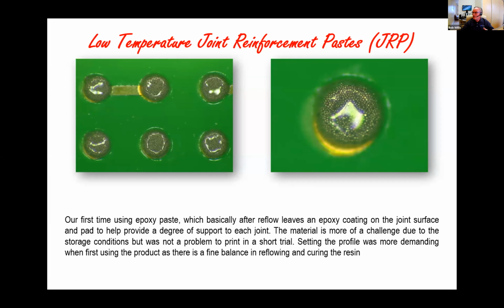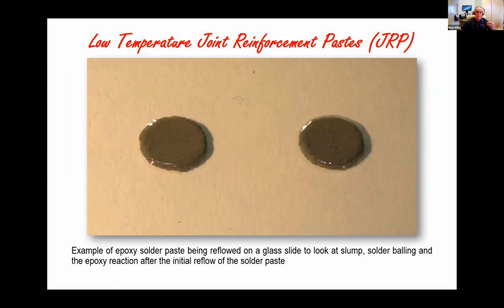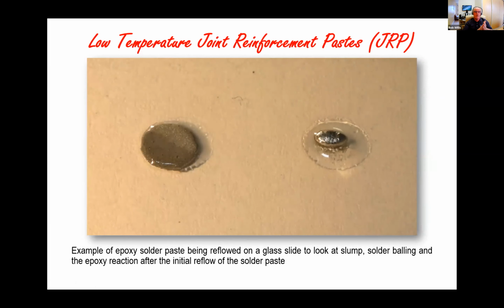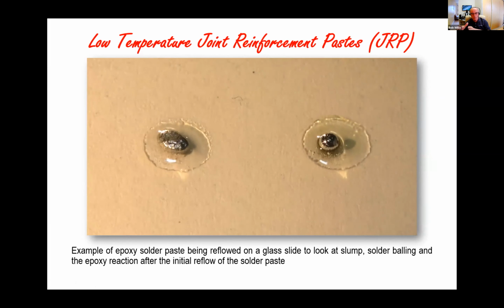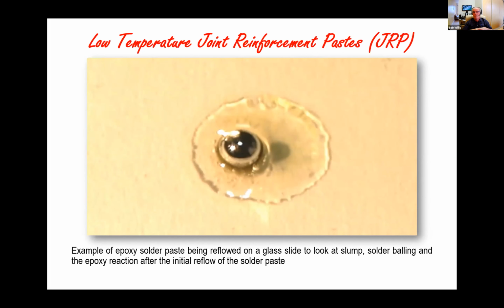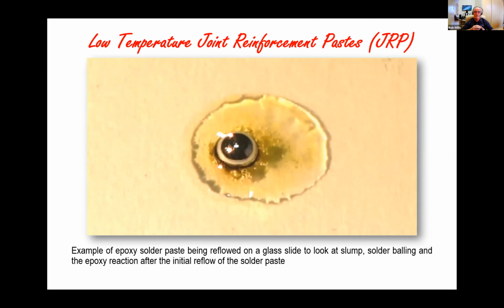And fundamentally, the JRP materials are solder paste. But the interesting thing is they have an epoxy resin system within the non-metallic material, which makes up the solder paste. So when we actually take the material and reflow it, we're doing two things. We're making a mechanical, but also an electrical interconnection. So if you look at a close-up of some of these reinforcement pastes reflowing, as I've done previously with the other materials you've seen, then if we go to close-up, you not only see the reflow characteristic, but you also start to see the reaction of the materials, which will actually provide what we want, which is the retention force.